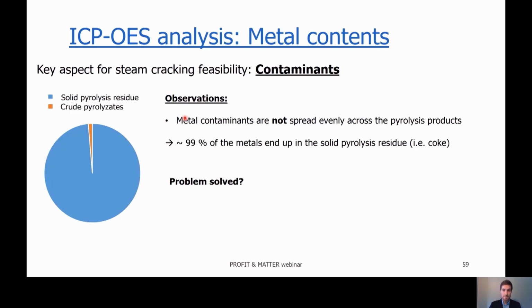What has been seen is that the metal contaminants are not spread evenly across the pyrolysis products, meaning most of the metals end up in the solid residue of the pyrolysis, which can be seen here in this pie chart. The blue part is the metal content of the solid pyrolysis residue, and the orange one is the crude pyrolysate's metal content. It can be seen that almost 99% of the metals end up in the solid pyrolysis residue, i.e. coke, remaining in the pyrolysis reactor, while only 1% ends up in the crude pyrolysate.